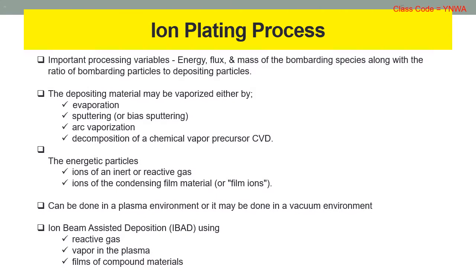Ion plating process. In ion plating, the energy, flux, and mass of the bombarding species along with the ratio of bombarding particles to depositing particles are important processing variables. The depositing material may be vaporized either by evaporation, sputtering, or bias sputtering, arc vaporization, or by decomposition of a chemical vapor precursor, chemical vapor deposition, CVD. The energetic particles used for bombardment are usually ions of an inert or reactive gas, or, in some cases, ions of the condensing film material, or film ions.